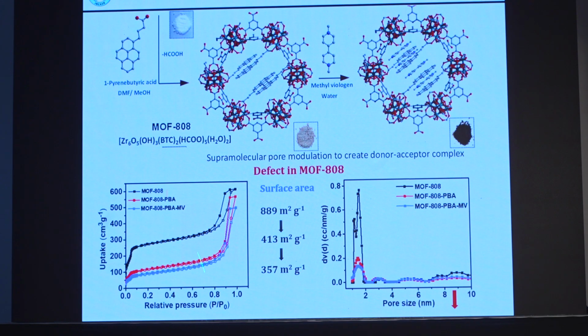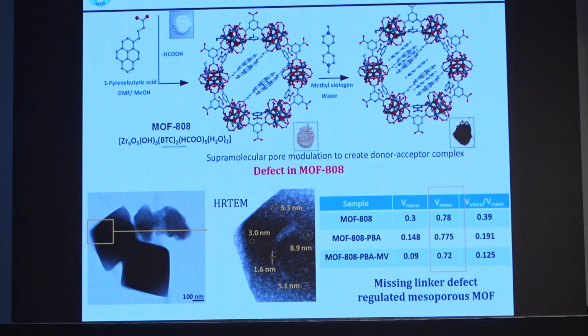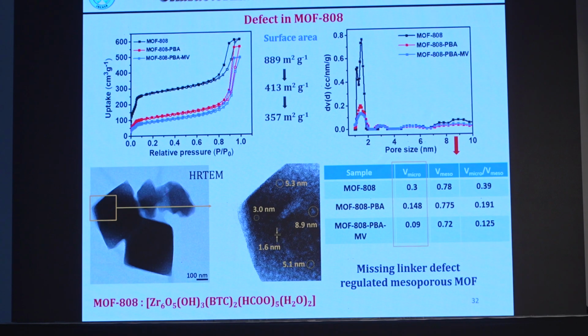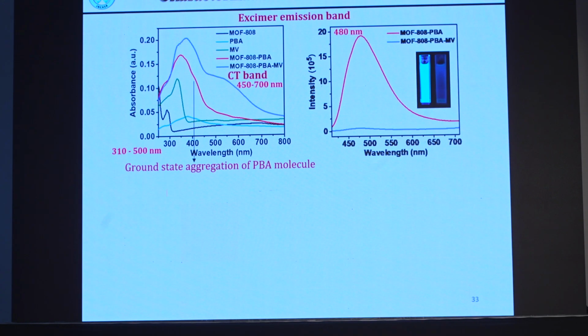So there you can see when we further decrease the surface area, the pore volume decreases here, and you have this HRTEM showing the mesoporosity, okay, high resolution. Now if you look at the color, when I have the pyrene butyric acid, this has this cyan emission because it forms the excimer inside the MOF. When I put in the methyl viologen, that donor-acceptor charge transfer complex forms, and I get the CT band, and the emission vanishes. When there is charge separation, that emission will not be there.